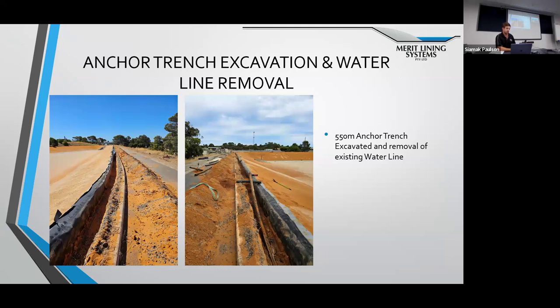Additionally, we had to remove the geomembrane from the anchor trench. So you see there was 550 linear meters of anchor trench we had to open up. And in that trench, there was an existing water line, which was removed from the trench.